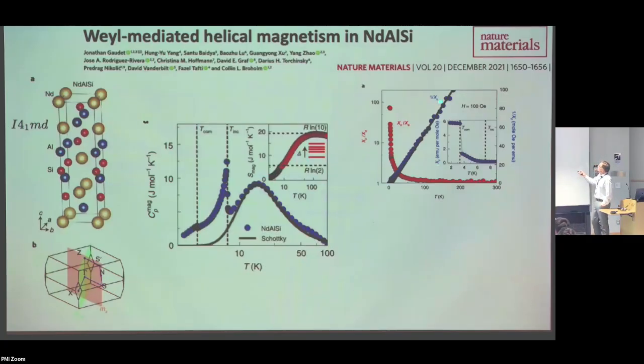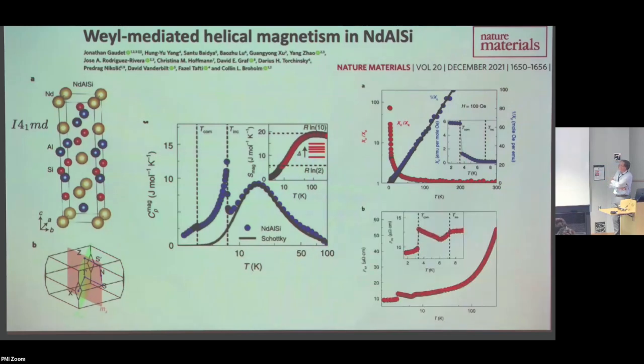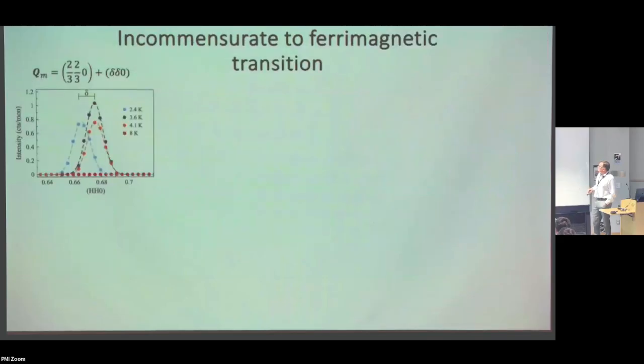We also notice that the system eventually develops, in the commensurate phase, a little ferrimagnetic component to the moment as well. The susceptibility gets flat because it's really a finite magnetization that develops in this field. We'll see why that has to happen. That doesn't always have to happen, but it does in this case. There are little anomalies in the longitudinal resistivity as you go through these transitions, and that indicates some kind of rearrangement of the Fermi surface resulting from the exchange field from the ordered spin structure.